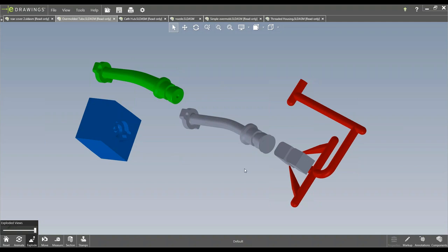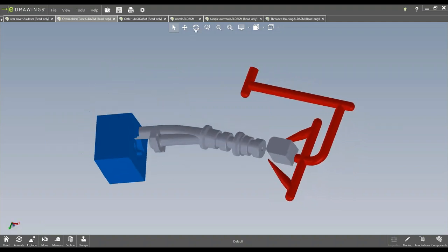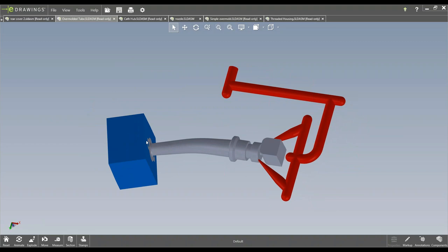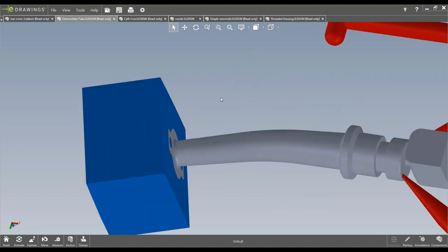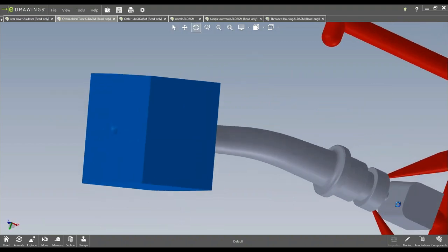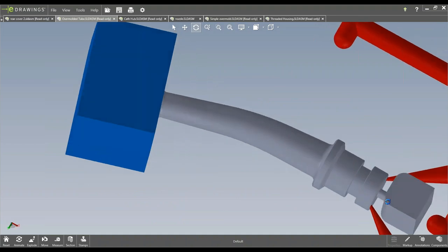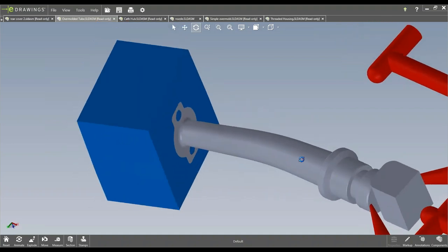So that's what this jacket kind of came in. And then we have a couple of hand loads, as you can see here, to create this on here. And there's another one here. So there is actually a thin wire that would ride into the tube. It was a Teflon coated length and diameter bend to it that had to be pretty much exact in order to fill that part correctly with proper wall thickness on all sides.